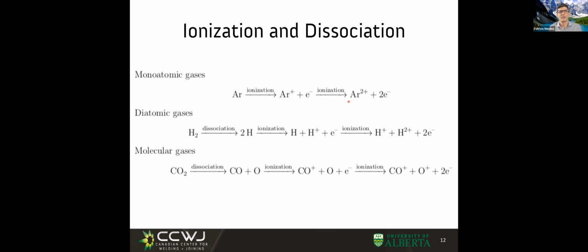let's talk about what plasmas are, right? So a normal gas, whether it's air, or argon, which is inert, or hydrogen, which is diatomic, for example, in 6010 or 6011 electrodes, which are both cellulosic, when they burn, they generate a lot of hydrogen, H2. Or you can have molecular gases, like for example, if you're doing MIG welding with pure CO2 or argon-CO2 mixes.